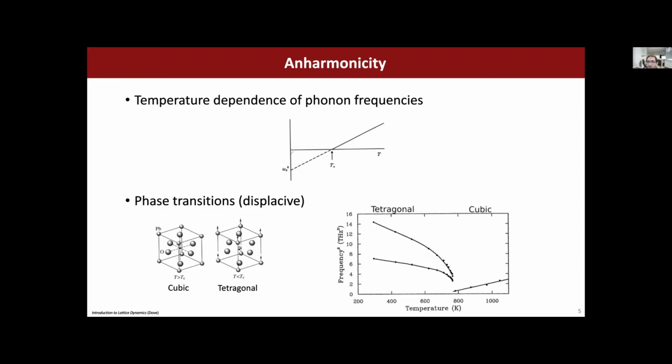Also, you might notice that the bottom part are imaginary frequencies. So the plot shows you that the structure for which the computation was done is actually unstable when you go below the critical temperature Tc. And this also gives you a way to talk about phase transitions.